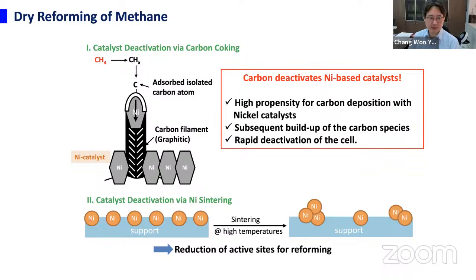And another problem is nickel sintering. Nickel sintering means nickel aggregation at high temperature. At first, before the reaction, the nickel species is well dispersed on the support. But after the reaction goes on at high temperatures, surface diffusion of this nickel happens, and nickel aggregates to form deactivated species. So we need to develop relevant technologies to prevent this kind of catalyst deactivation.